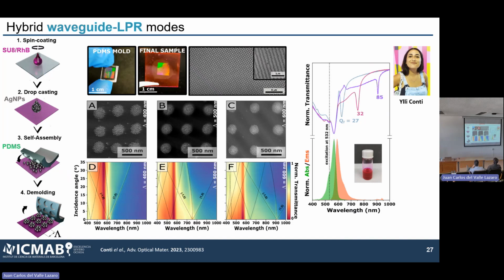And interestingly, all this is done without embedding our metasurfaces in a PDMS layer. So these are all open cavity. So we dug a little bit in the literature, trying to figure out why we could see these sharp resonances without embedding the system. And it turned out that what's going on is that we have some waveguided mode. And so you have a hybridization between our plasmonic response and the waveguide mode. And this basically allows for the emergence of these lattice resonances even without the matched supra layer.